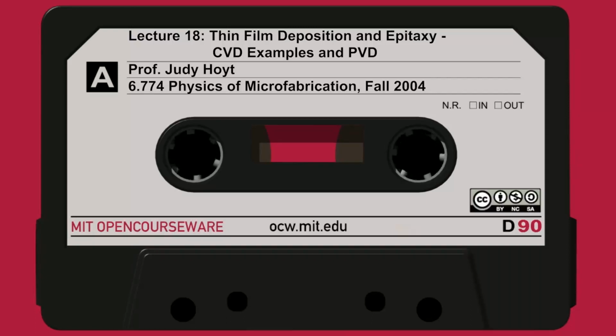The dep rate of some elements is going to be very slow because the evaporation rate is low. Its vapor pressure may be low. One thing, well, good point though, is it's very difficult to evaporate alloys or compounds. As you can see, depending on the material, between aluminum and nickel or chromium and nickel or whatever, at a given temperature, their vapor pressures vary by orders of magnitude. And so if you put in your little crucible a little bit of one element, a little bit of another element, they're going to come off at very different rates. So trying to evaporate a compound is tricky. You probably need 2 crucibles with their temperatures controlled electronically very carefully. So that gets a little tricky.